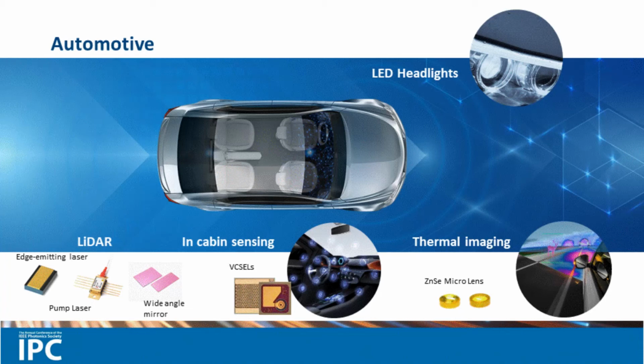By now, everyone is quite familiar with the promise of LiDAR to map the 3D terrain in front of and around the automobile. Multiple different LiDAR technologies are being developed, again leveraging the foundations from industrial materials processing and optical communications. These range from edge-emitting multi-junction pulsed gallium arsenide lasers at 905 nanometers to frequency-modulated continuous wave indium phosphide lasers operating at 1550 nanometers. On the receive side, multi-layer dielectric stack filters with wide acceptance angles were invented to filter out background light over the required wide viewing range.